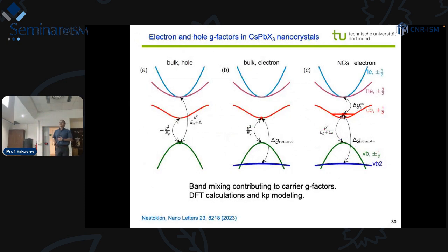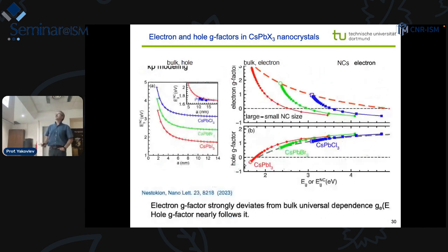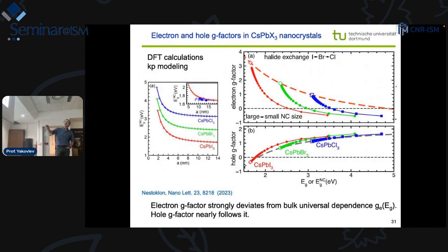Now, what happens if we go from bulk materials to nanocrystals? In this case, again, Misha Nestoklon made a calculation. He says that additionally, in nanocrystals, there is an admixture of the spin-orbit bands, which was absent for the bulk materials, for electrons and for holes. This admixture makes strong changes to the g factors. The dashed line here is what we expect from the bulk, the g factor as a function of energy.